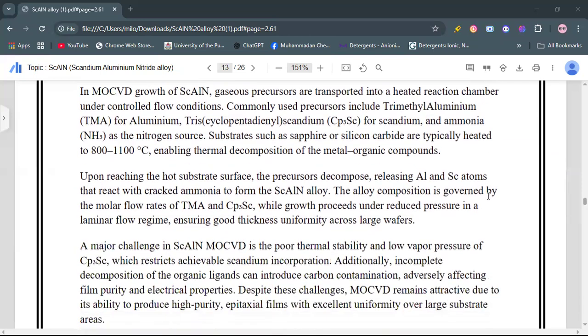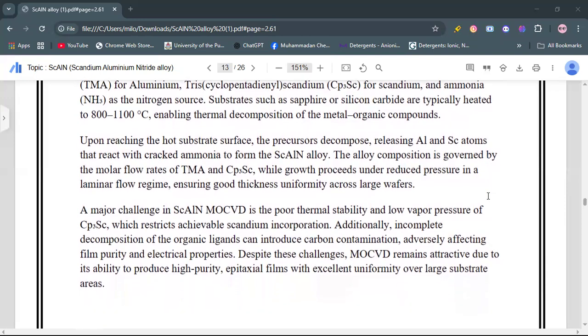Upon reaching the hot substrate surface, the precursor decomposes, releasing aluminum and scandium atoms that react with cracked ammonia to form the alloy. The alloy composition is governed by the molar flow rates of TMA and tris cyclopentadienyl scandium, while growth proceeds under reduced pressure in a laminar flow regime, ensuring good thickness uniformity across large wafers. A major challenge in this alloy is the poor thermal stability and low vapor pressure of tris cyclopentadienyl scandium, which restricts achievable scandium incorporation. Additionally, incomplete decomposition of the organic ligands can introduce carbon contamination, adversely affecting film purity and electrical properties.